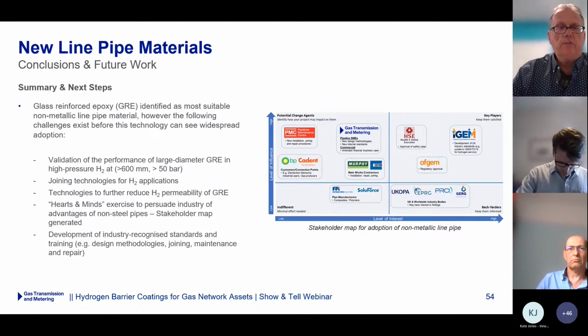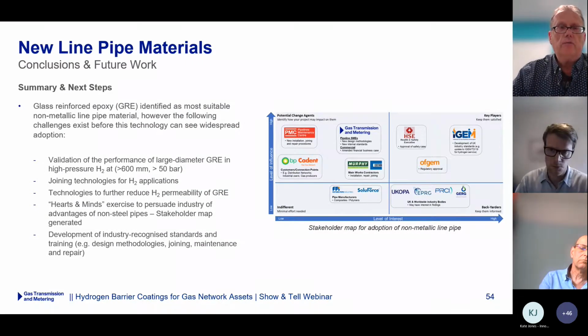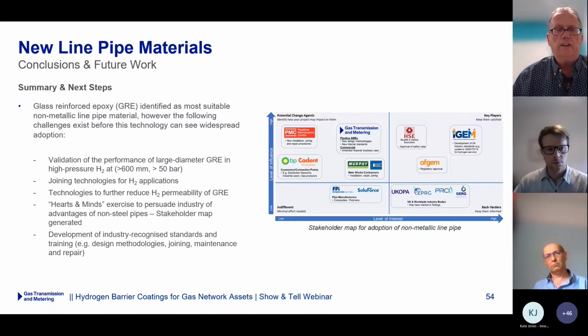So in terms of summary, in terms of replacing steel pipes with composite pipes, glass reinforced epoxy pipes are currently probably the most suitable. The technology is basically available. There are some issues that need some attention. For example, if we go to really high pressure, higher than 50 bar, close to 90 bar, the current pipes on the market are not all there. And also in terms of very large diameters for hydrogen at these very high pressures, I think at the moment most piping systems are at 600 millimeters. If you want 1 meter, that would need some development.